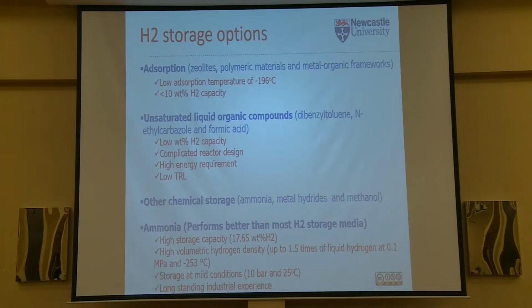The other class of materials include the unsaturated liquid hydrocarbons like formic acid and the rest of them. The problem with this class of storage materials is that, for the best of them, the hydrogen storage capacity is relatively low, less than 10 weight%. And of course, the reactors are complicated to design and they have high energy requirements, etc. Then you have chemical storage that includes ammonia, metal hydrides, and methanol.